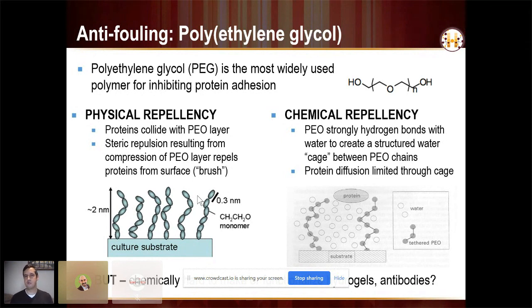There's also some emerging concern about PEG-based antibodies, because PEG is in so many things that we are exposed to day to day. And the current rough estimate is about 40% of us have at least some form of a PEG antibody. And this is actually one of the reasons why people might have a response to the COVID vaccine, the Moderna and Pfizer vaccines, because they do have PEG stabilizers in the nanoparticles. So if we can avoid that antibody response, which is an emerging problem, again, controversial, but still something that we would like to avoid if possible, it would be good.